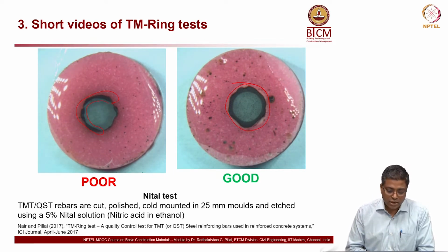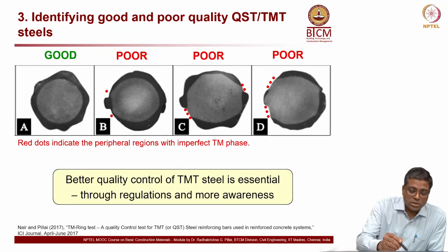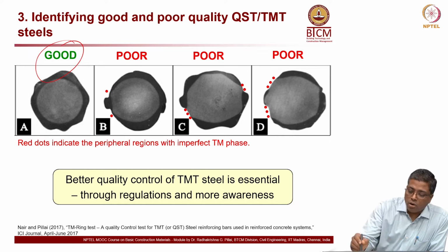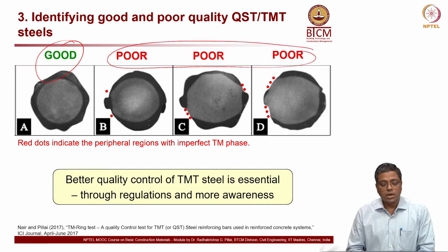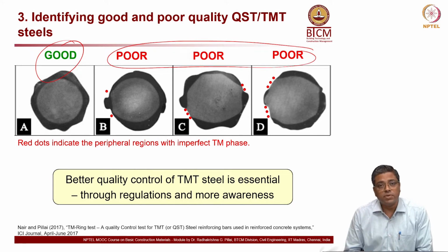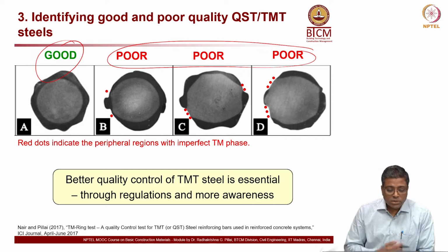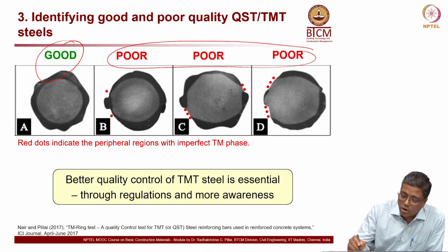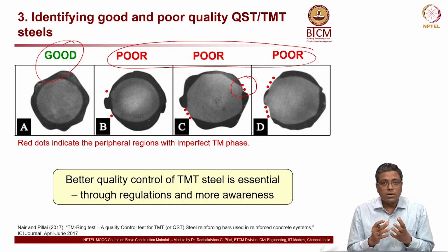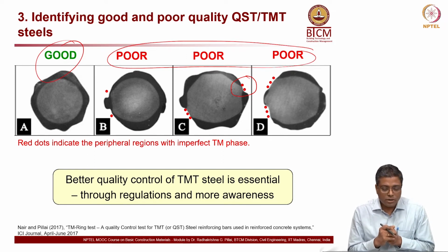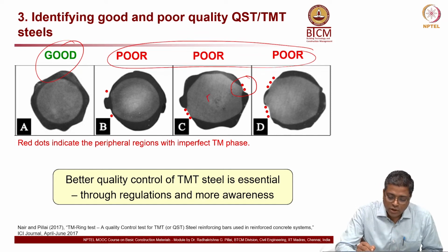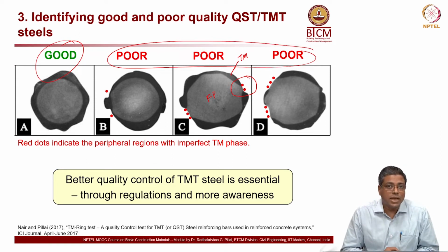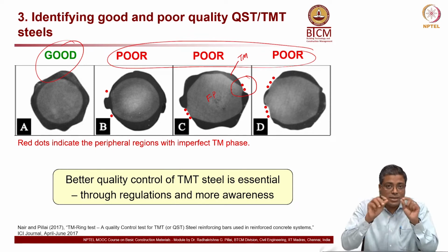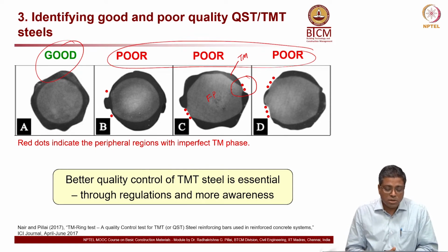You can very clearly see that in the ring test. Okay, now these are examples. Again here, this one is a good one, and all these are poor quality. All the three photographs on the right side indicate poor quality rebar. And unfortunately, we have a lot of such rebars in the market. What is the problem here is, I have indicated the red dots here. So for example, you look at this region, you have the tempered martensite, which is the dark gray color, ferrite pearlite, which is this, and then this is TM, right? So there is a discontinuity in the ring, or the ring thickness is not uniform. So these are all the problems.